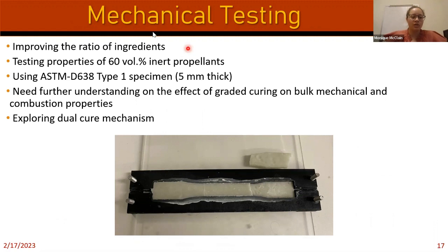So we've essentially started tweaking the ratio of these ingredients because again, that oligomer is very, very viscous, and we probably had too much of a content of that HCDA mixed with that oligomer. So we've tried to improve that ratio. We're trying to do some tensile testing of some inert propellants. So here's an example of one of those here. And it's not necessarily a successful sample, but the point is to demonstrate here, we have a dog bone type 1 specimen. It's 5 millimeters thick. So we cure from both sides.